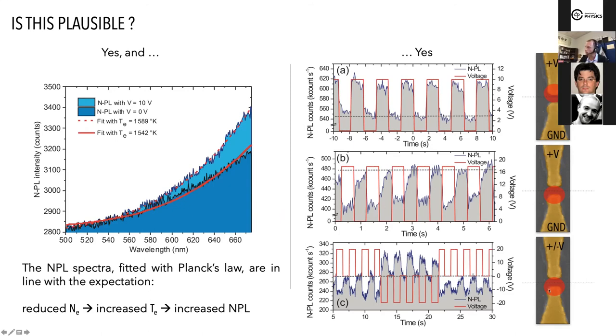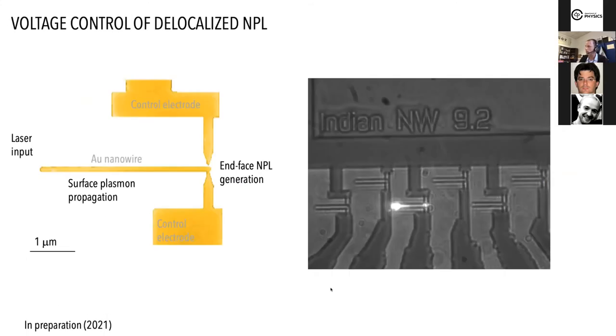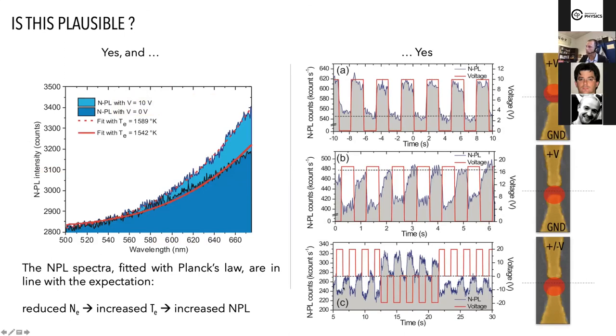And then the final proof is that, locating there, we change the polarity, and we go from a quenching whenever you have a bias to a 180 degree phase shift between the bias and the NPL response. When we have a negative bias, we have an enhancement of the NPL. So this is very much consistent with this picture. Okay, last slide before I conclude.